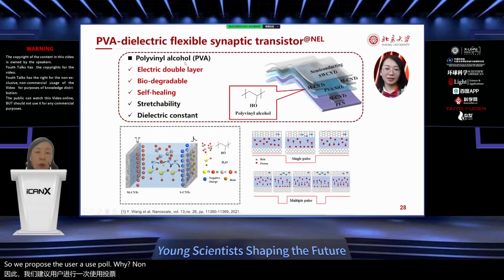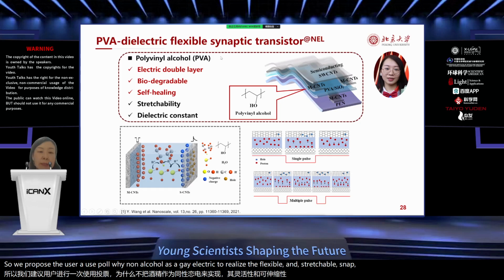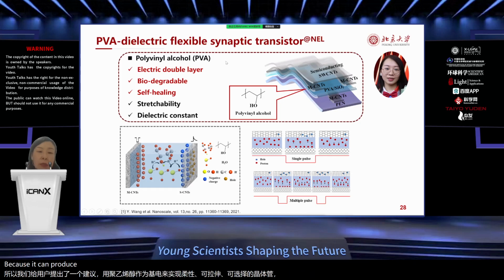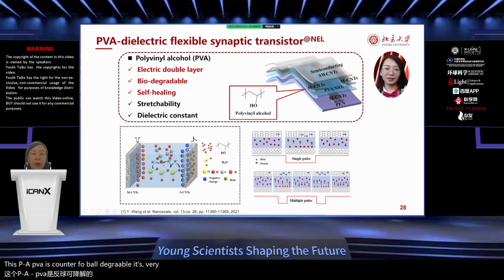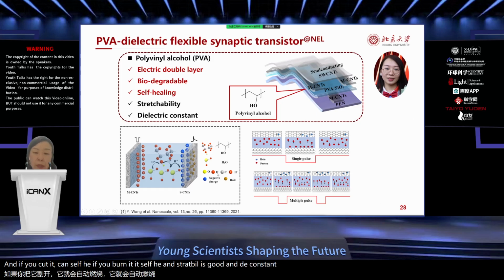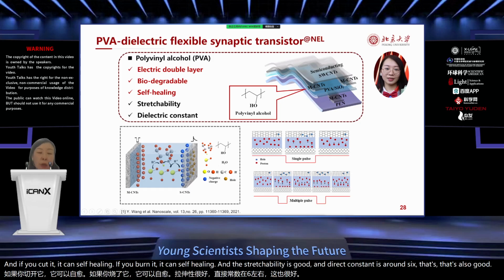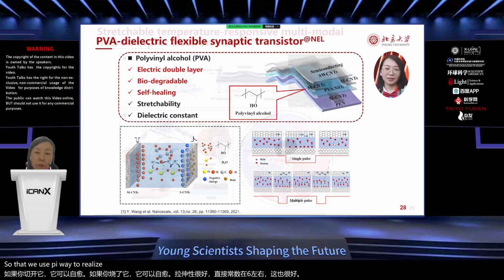So we propose to use polyvinyl alcohol as a gate dielectric to realize flexible and stretchable synaptic transistors, because it can produce an electrical double layer as a dielectric, and also this PVA is biodegradable. It's very environmentally friendly. And if you cut it, it can self-heal. If you burn it, it can self-heal. And the stretchability is good, and the dielectric constant is around 6. That's also good.